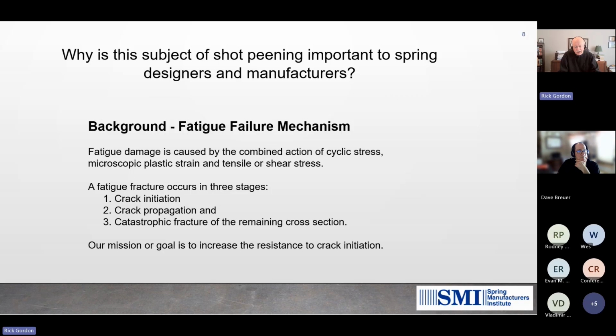So why is the subject of shot peening important to spring designers and manufacturers? In our advanced spring design class 301, Springs Fatigue, we discuss failures that occur in springs. As we categorize spring failures that we see in our failure analysis work, there are several mechanisms that are involved. And what SMI has found and others have reported is that over 50% of failures are due to fatigue. Now, fatigue damage is caused by a combination of actions of cyclic stress, microscopic plastic strain, and tensile or shear stress. What we've learned is a fatigue fracture occurs in 3 stages: crack initiation, crack propagation, and then catastrophic fracture of the remaining cross-section.